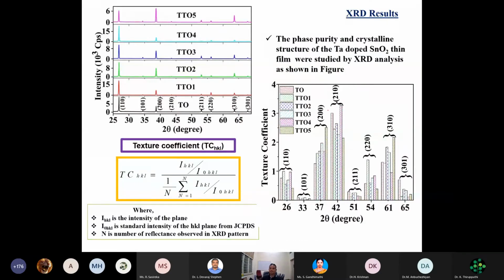Then coming to the X-ray diffraction. Now you recall the X-ray diffraction which I told you. Now we have estimated the texture coefficient for this set of thin films: pure tin oxide, and then 1%, 2%, 3%, 4%, 5% tantalum doped. And you see that the texture coefficient is higher for the 210 direction. So that means the particles on the surface of my film are already oriented along a particular direction. This orientation is called anisotropy.